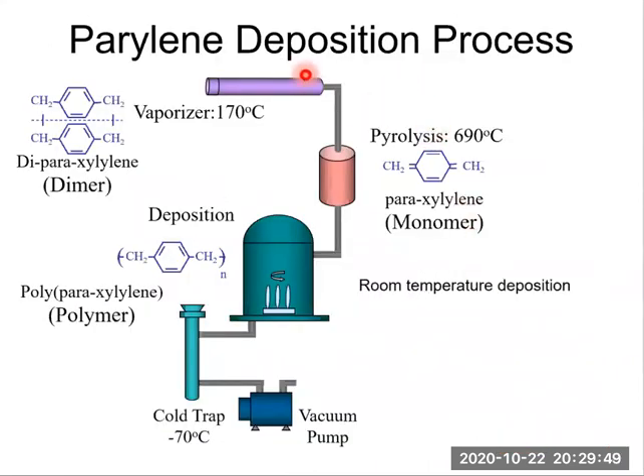This is a parylene deposition process. We start from parylene dimers, the two units here. So we call this molecule a dimer, parylene dimer. Parylene dimers are vaporized at 170 Celsius. So vaporized at this temperature.